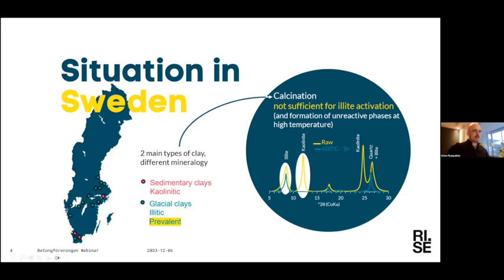This is illustrated in this graph, which is the XRD pattern of a clay containing both illite and kaolinite. In yellow is the raw material, and in blue is the material after calcination at 600 degrees. We see that for kaolinite, the peak disappeared. It shows that it's now amorphous and reactive, and then it participates in the hydration reaction of cement. But for illite, nothing really happens. And if we increase the temperature even more, we have the risk of forming unreactive phases, which would be even worse. So we still wanted to use our local resources in Sweden.